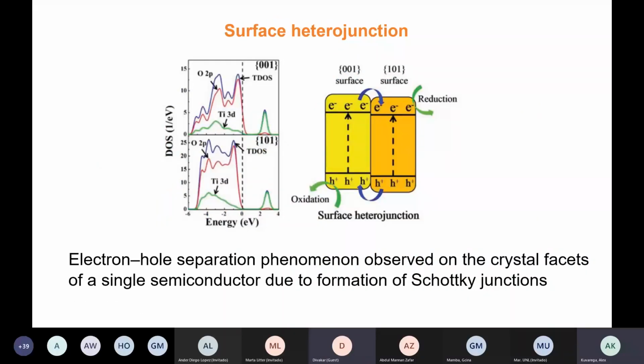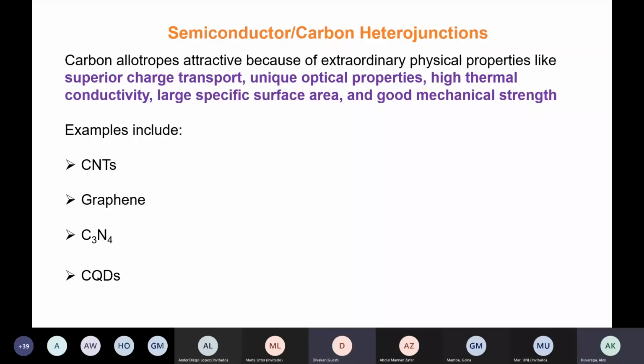And then we have the surface heterojunction, which can form the type 2 kind of heterojunctions, where you have specific surfaces within the semiconductor. It could be the 001 surface, it could be the 101 surface in the TiO2, resulting in channeling of electrons from one surface to another, and also channeling of holes from one surface to another, resulting in the formation of a Schottky barrier or a Schottky junction that will result in delayed electron hole recombination and therefore increase the efficiency in the degradation. And then the semiconductor carbon kind of heterojunctions.